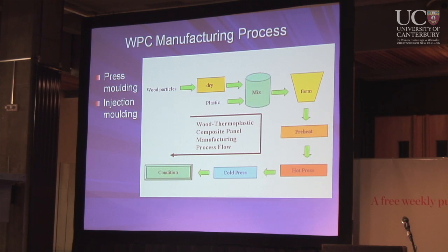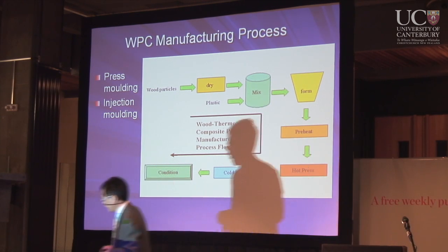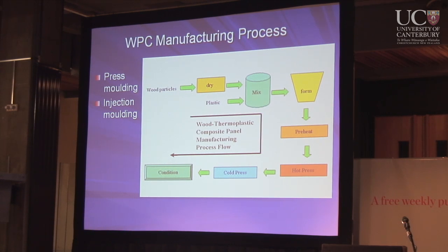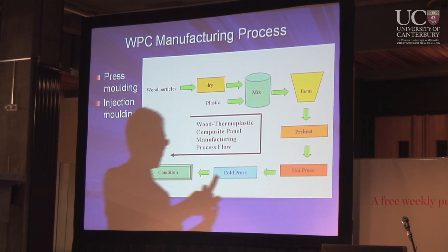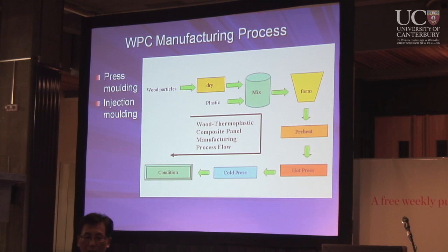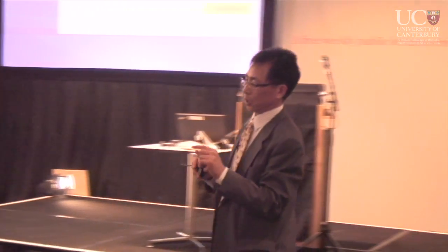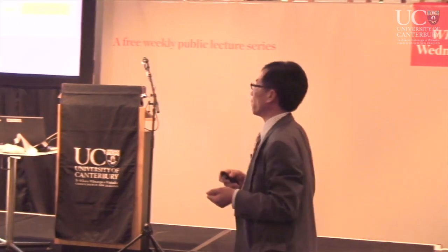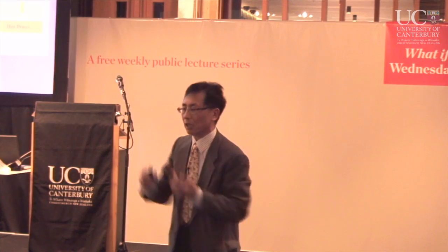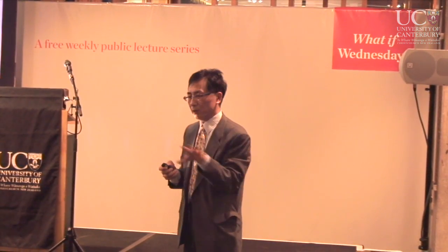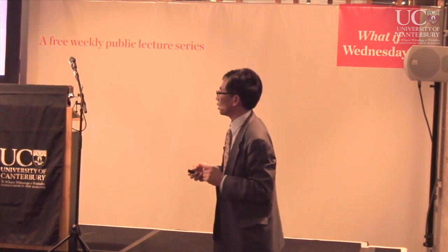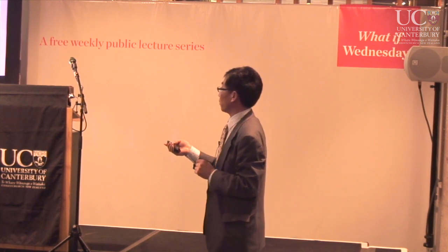What's the benefit of using hot press? The surface property is much better. If you look at the injection molding, two samples from a company that uses injection molding, you can feel the surface. You can see the surface is quite different. This surface is not as good as the hot pressed product. If you look at the flat sheet, the hot pressed product is very smooth and also very durable on the surface.